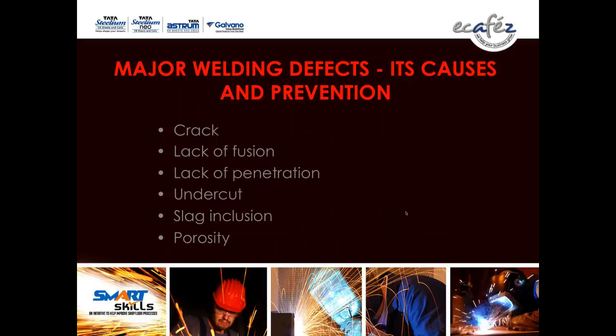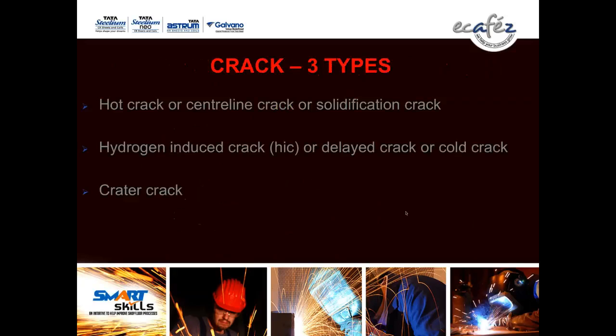Major welding defects, its causes and prevention. Major welding defects are crack, lack of fusion, lack of penetration, undercut, slag inclusion, and porosity. Crack may be of three types. Number one: hot crack, or center line crack, or solidification crack. Number two: hydrogen-induced crack, delayed crack or cold crack. Number three is crater crack.